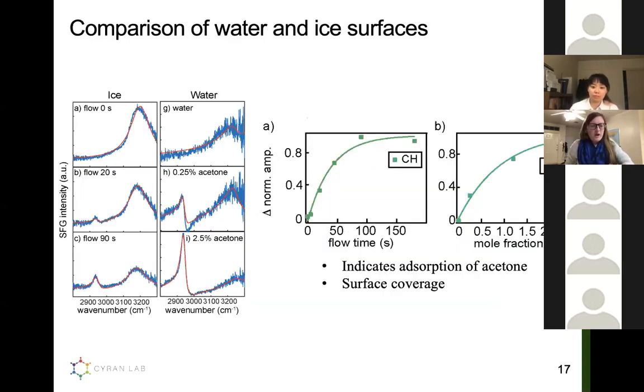So to go into a little bit about what this comparison means and what we can see, what I did is I looked at both water and ice surfaces. Here on the left-hand side, I have the spectra again. So we're looking at ice and also water. And what you can see is that the increase in the CH peak and the spectra themselves look quite different. And it's crazy, right? Because we're looking at ice, which is H2O molecules, and water, which is also H2O molecules. But we can see that the surface structure from the spectrum is very, very different, and how the acetone interacts is also very different.